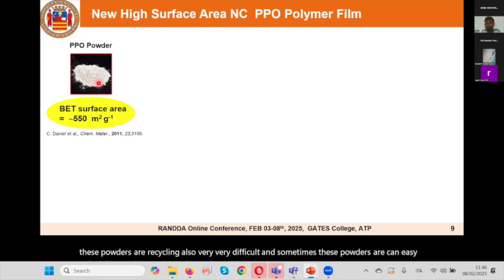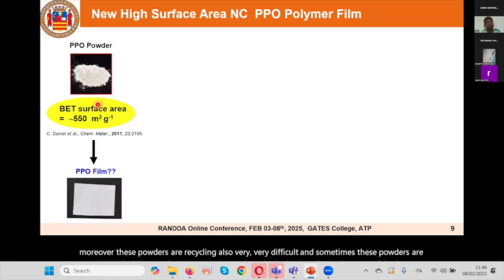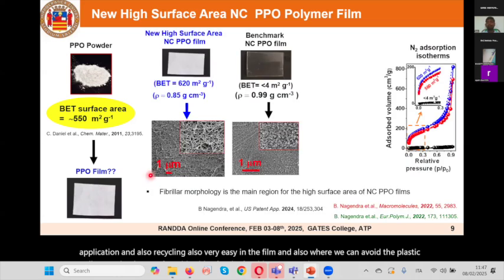Here, our objective is to bring all these surface functions to the polymer film, to the polymer surface. In the film state, applications are very huge, where you can extend to a very broad range of applications, recycling is also very easy in the film, and we can avoid plastic pollution. So that is one of our ideas. For this, we recently developed a new processing method. We were able to prepare a polymer film with a very high surface area, more than 620.